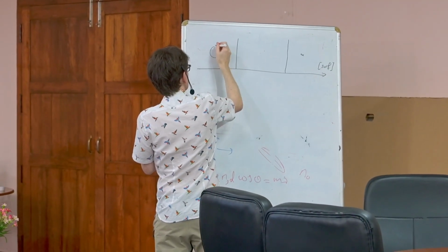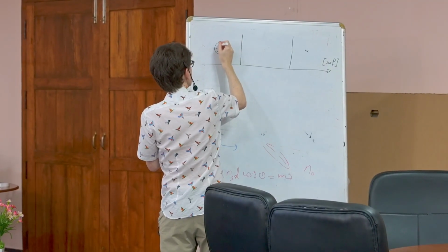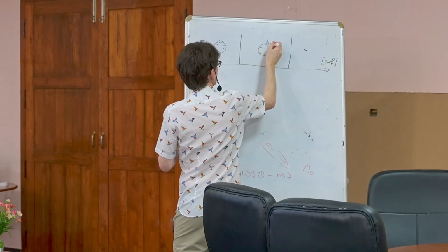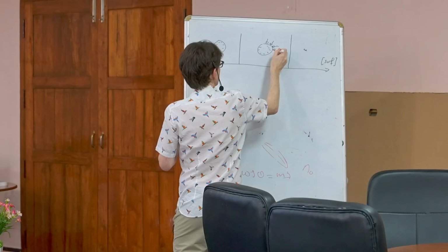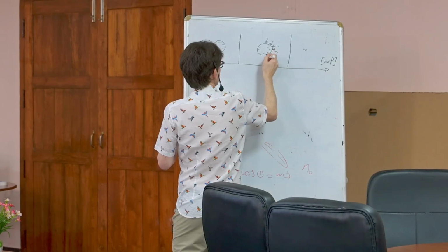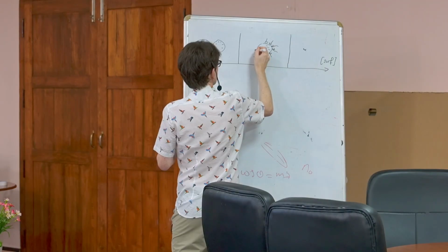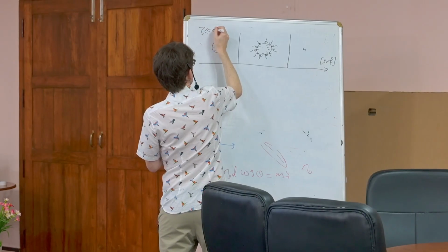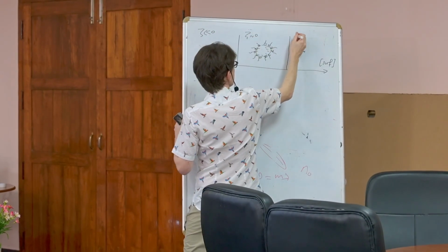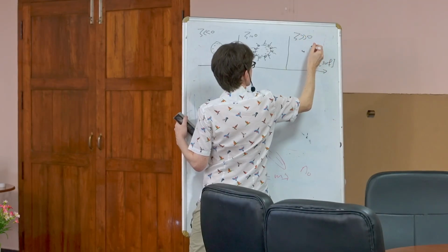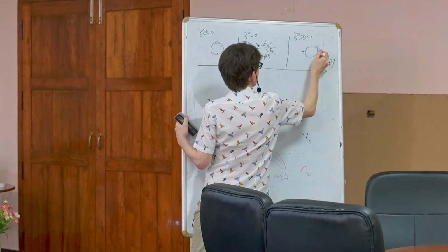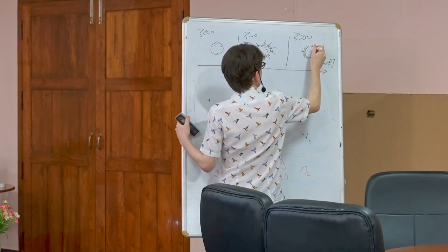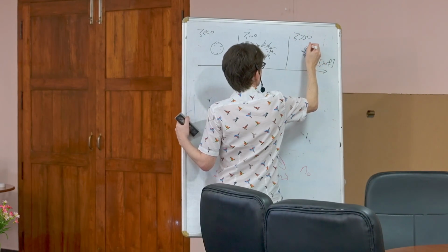My particle, I draw negatively charged, but it can be cationic, okay? Here, I am making a monolayer, and I neutralize the particle. Here my zeta potential is strongly negative, here my zeta potential becomes almost zero, and here my zeta potential becomes overcharged. And this also works for the opposite charge system, so cationic particles and anionic surfactant.